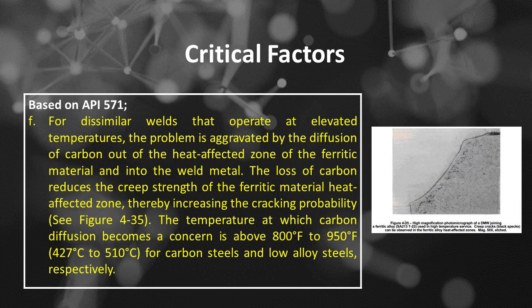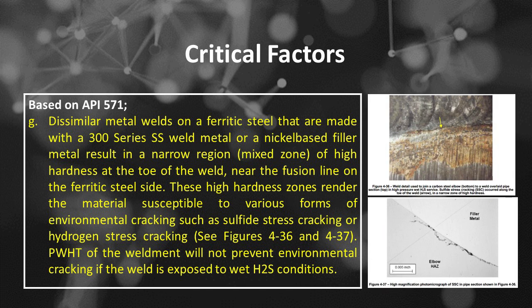Mag. 50X, etched. Dissimilar metal welds on a ferritic steel that are made with a 300 series SS weld metal or a nickel-based filler metal result in a narrow region, mixed zone, of high hardness at the toe of the weld, near the fusion line on the ferritic steel side. These high hardness zones render the material susceptible to various forms of environmental cracking such as sulfide stress cracking or hydrogen stress cracking. PWHT of the weldment will not prevent environmental cracking if the weld is exposed to wet H2S